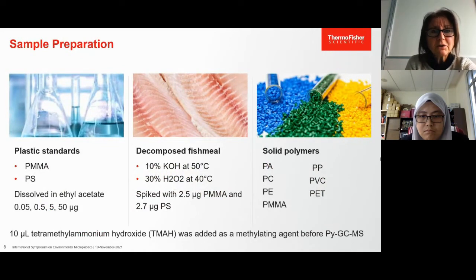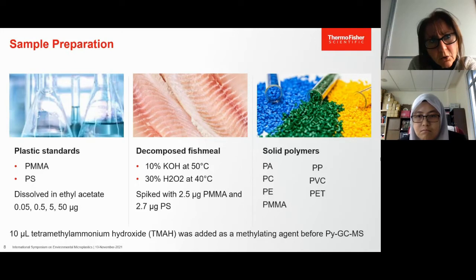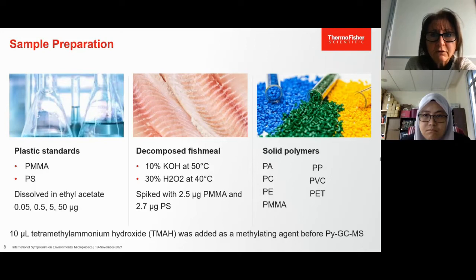The applicability of the Orbitrap GC-MS in combination with pyrolysis for qualitative and quantitative assessment was tested using both commercial plastic standards and fish meal samples, which have been spiked with a known amount of plastic polymers. Between 0.3 and 0.5 grams of fish meal resulted in about 5 to 10 milligrams of decomposed material, which was spiked with 2.5 microgram of polymethyl methacrylate and 2.7 microgram of polystyrene in the ethyl acetate standard solution.